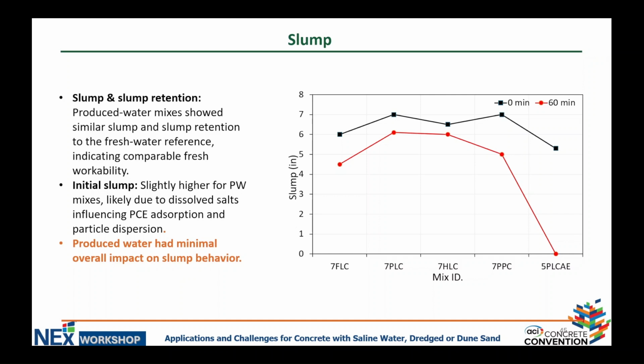We can see that produced water mixes, in general, have slightly higher slump. That's not very high, but slightly, 1 inch higher slump. Most probably, this is related to the dissolved salts helping or aiding the PCE admixture to work more effectively. As we can see from the results, simply the produced water is not really impacting slump in a bad way.